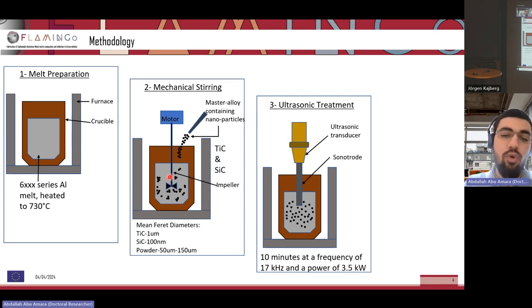So essentially we apply some ultrasound waves in this composite melt. And the idea is to produce some ultrasonic cavitation that can then disperse the particles even further. We really need a homogeneous distribution of the particles in the melt in order to achieve the best mechanical properties. If we have agglomerations or some clusters in the melt, then that can create weak spots in the material once it solidifies. So this is why we try our best to achieve the most homogeneous distribution of the particles. So we apply the ultrasound for approximately 10 minutes at a frequency of 17 kilohertz.